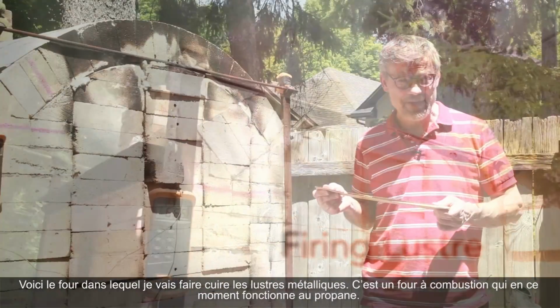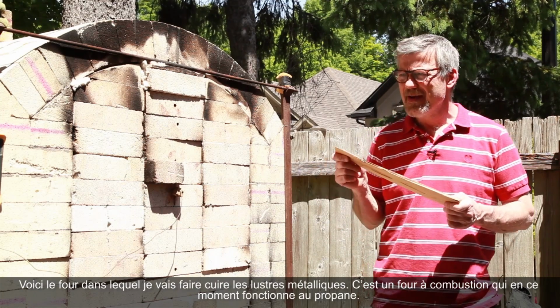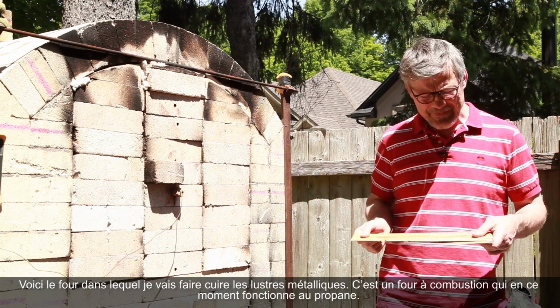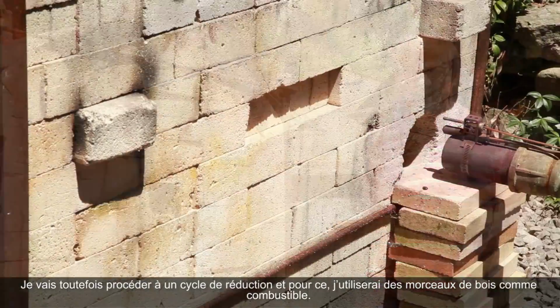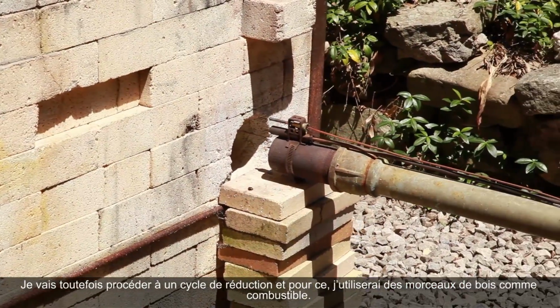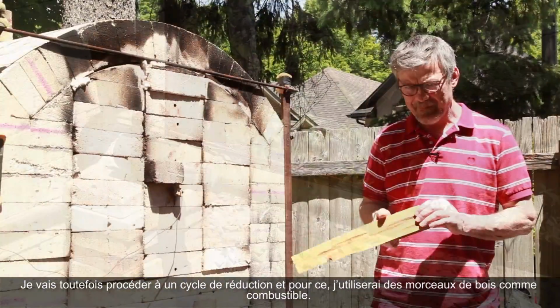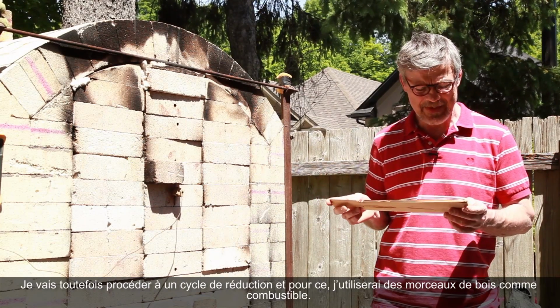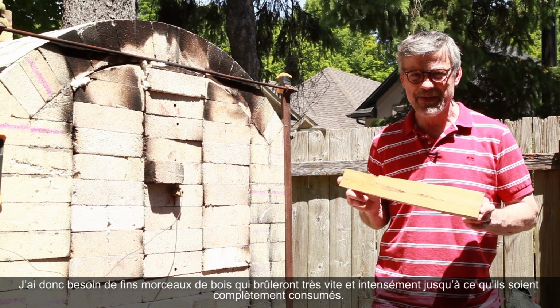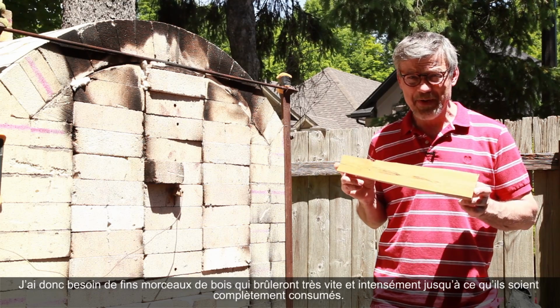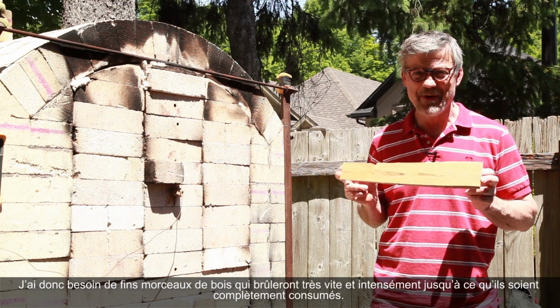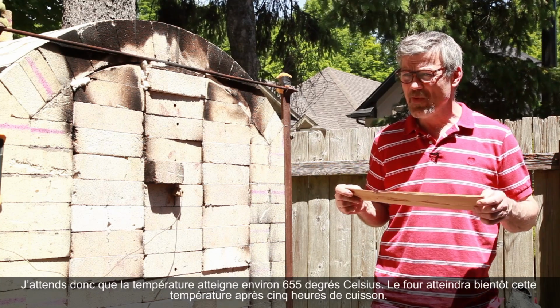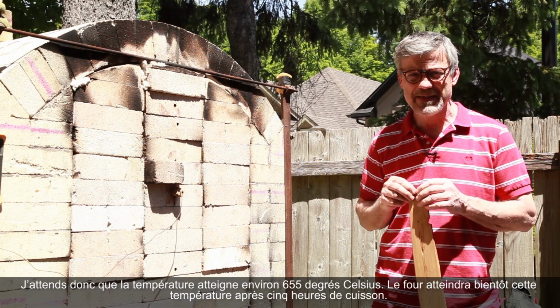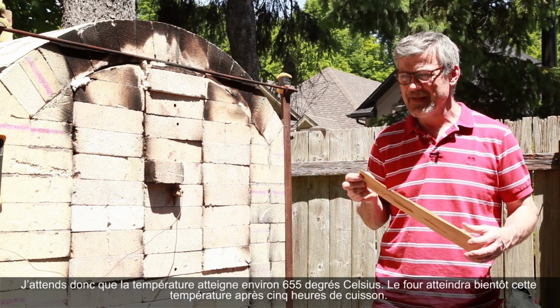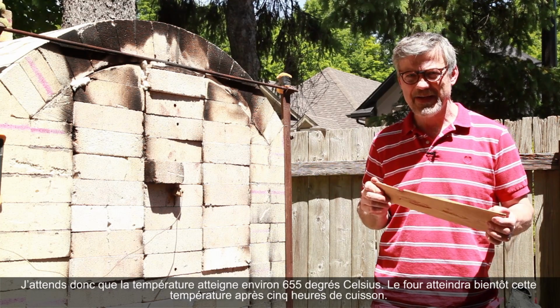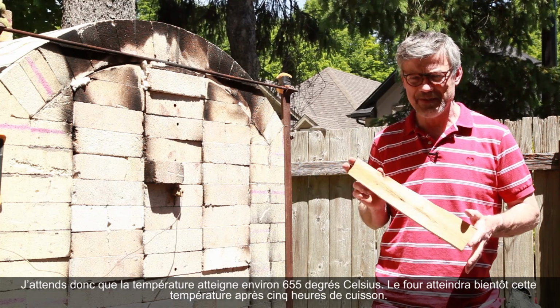This is the kiln that I'm firing luster in. It's a fuel burning kiln, and at this point it's fired with propane, but I'm going to also do a really profound cycle of reduction using wooden shingles in this case. What I need are really thin strips of wood that will burn really fast and really hard and then be burned up. So I'm waiting for a temperature of about 655 Celsius. It's been on about 5 hours now, and I'm just coming up to that temperature soon.